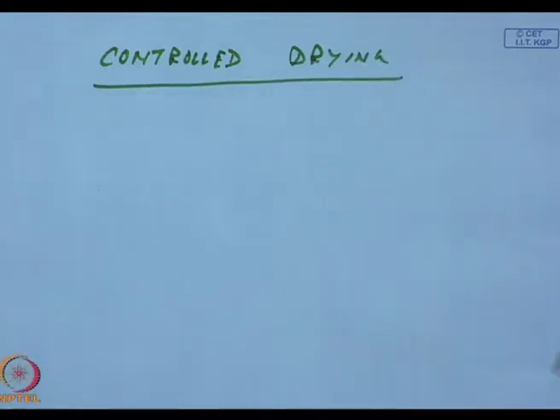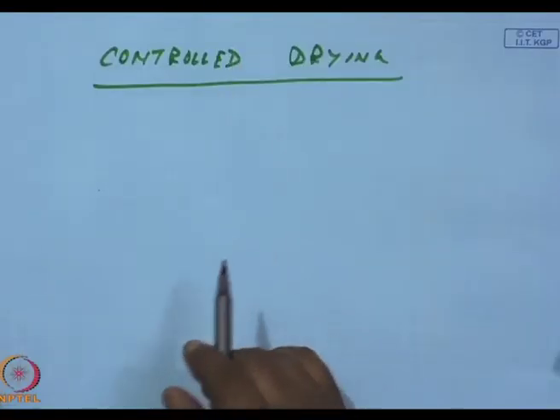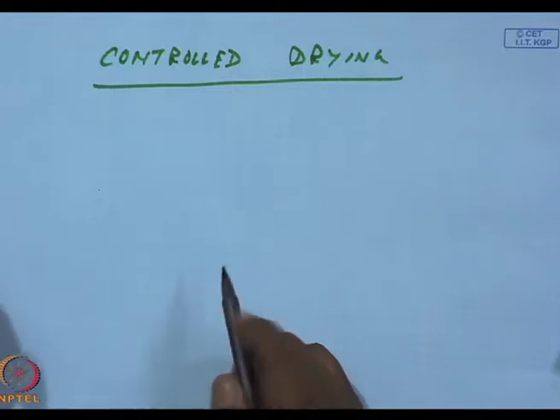So, what is done is controlled drying, which is almost akin to what I talked of when I was talking of fabrication of xerogels from alkoxides. I told you that I would control the temperature, the relative humidity, so that the pores collapsed uniformly and the material did not fracture. So, here my only avenue is to have controlled drying. And how is it done?